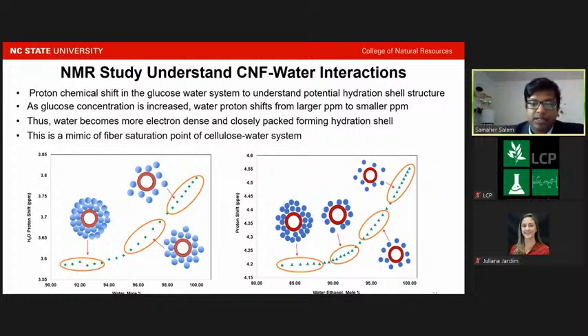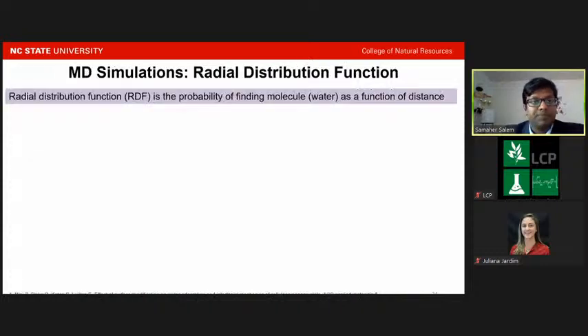it took a longer time and a higher concentration to get saturated for the water-ethanol system. And it shows that when we add the ethanol, the hydration shell is not as compact as in the water-only system. Thus, the water-ethanol system could facilitate more anhydride groups to the reaction site and increase the reactivity of the system.